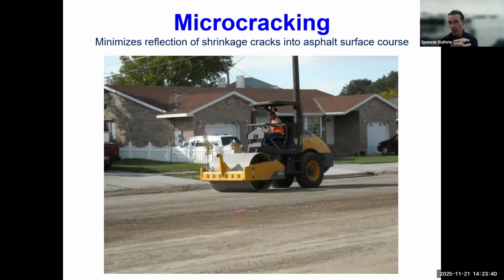So when I was at Texas A&M, where we use a lot of cement treatment and lime treatment and had a lot of this cracking problem, we had to figure out a way to stop it. And so my research group designed an experiment where we introduced a new technique to the industry called microcracking. You might also see it in our early publications called pre-cracking.